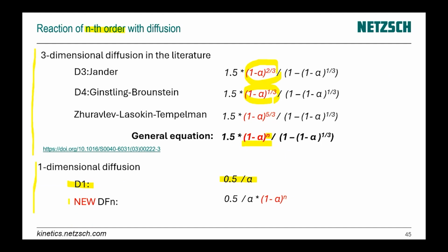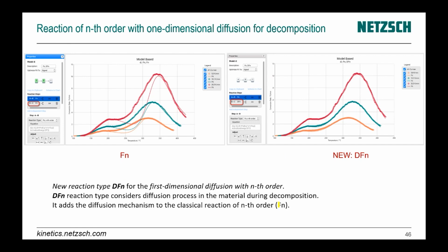And now we have created a new reaction type with this additional part. If n is equal to 0, then we have the classical reaction of 1-dimensional diffusion. If n is not 0, then we have a reaction which at the beginning has diffusion and at the end has the shape of nth order reaction. Why is it important? Because for many reactions, really for many reactions, we have a shape where at the beginning, here, for example, for the main peak, the reaction goes much slower than the nth order reaction. It means that here some diffusion happens. And the final part looks like nth order reaction without any problem.